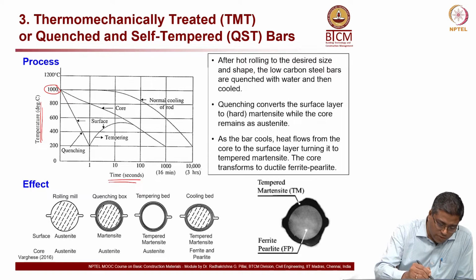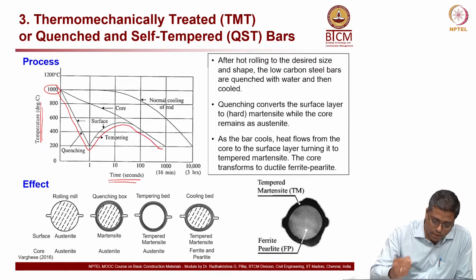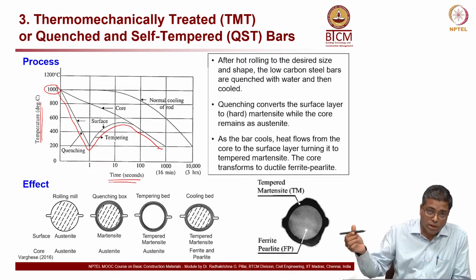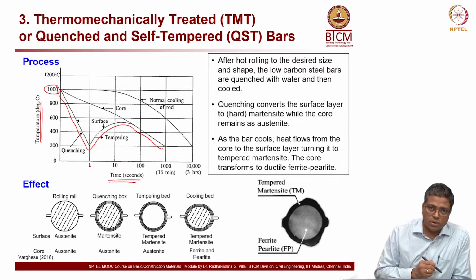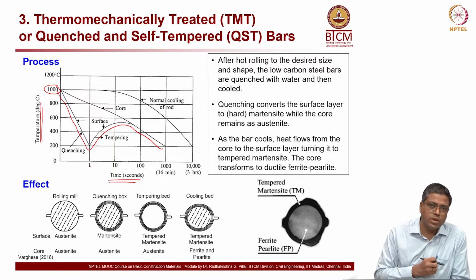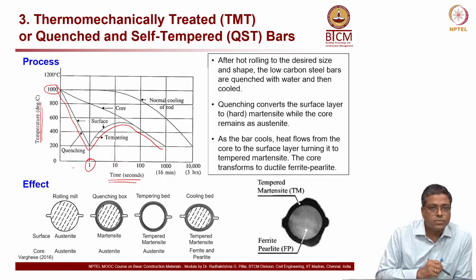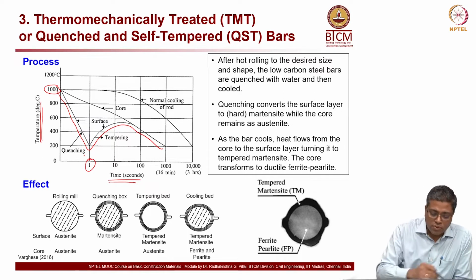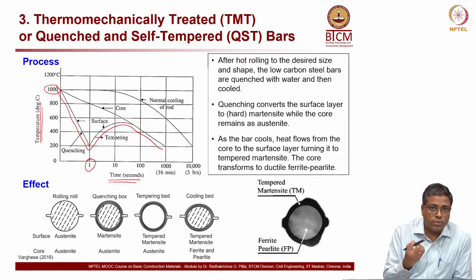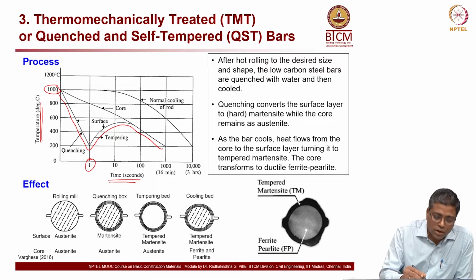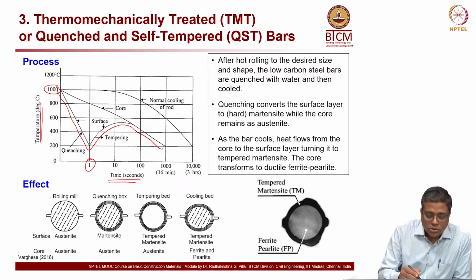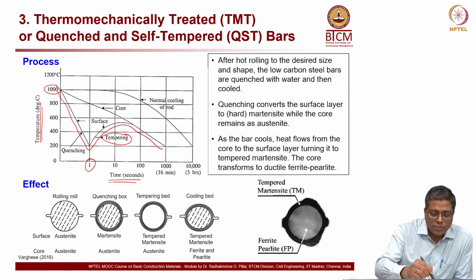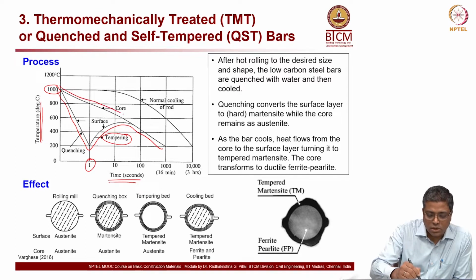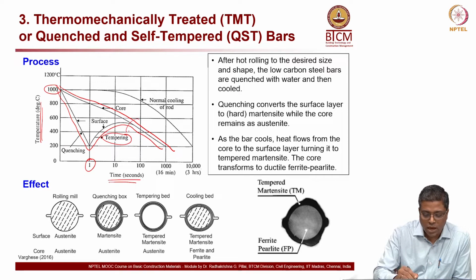So what happens is the surface temperature follows this curve. The moment the bar goes through the water bath, it gets quenched in the water. So the hot steel comes in contact with the cold water for 1 second, and then suddenly it comes out of the water bath, and the center of the steel, the core region, is still very hot, right? So that heat also radiates outward, and then it heats the surface again. So that is what we call the tempering process. You can see the temperature increases again, and eventually it matches with the temperature of the core, which is this curve here. So this matching happens here.